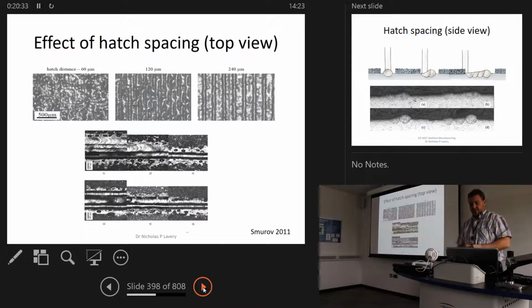If we look at that, we can see here some variations when smaller hatch spacing up to larger hatch spacing is used. So from 60 to almost 250 micron, 240 micron. On the right-hand side of the picture, you can see very clear single tracks, but with no overlap whatsoever. Right? So they look good, but they aren't going to necessarily be very well bonded together. The 120 micron spacing there in the middle, in the top middle, shows that there is a lot more bonding going on between the tracks.